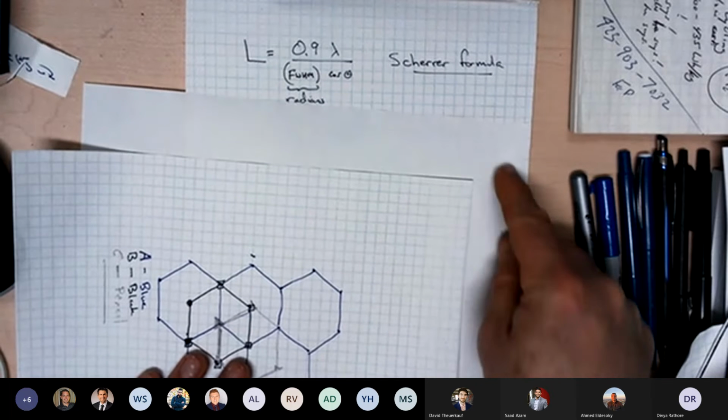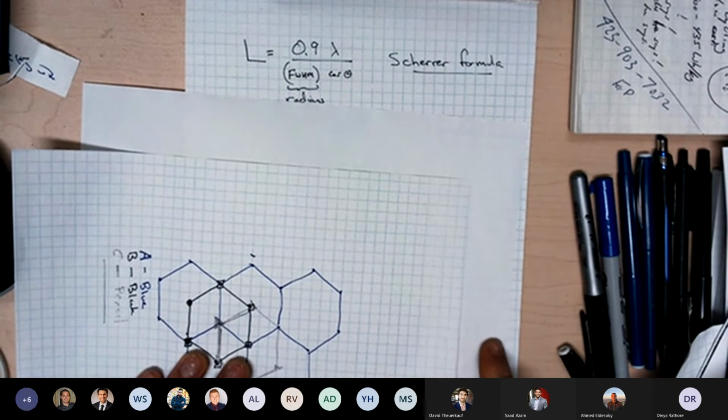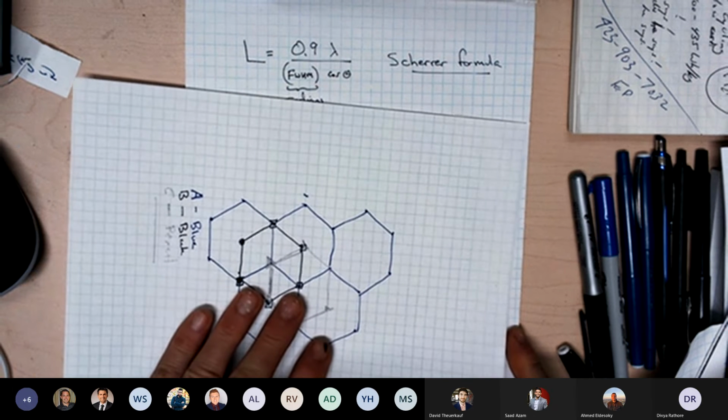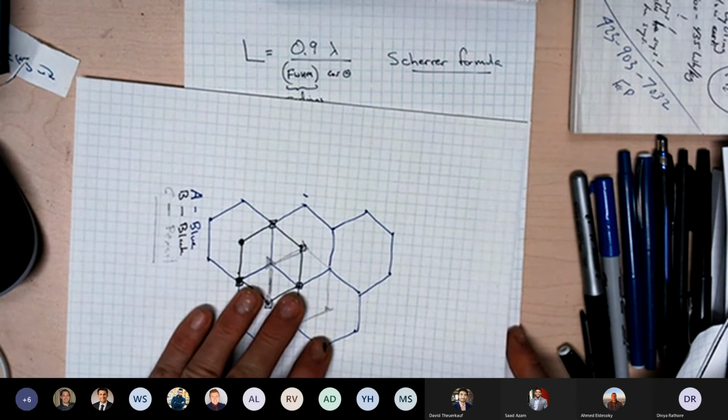I've got two graphene sheets. They're in AB stacking. Maybe I'll turn one of them over. Okay, so there's a white one and this one. You put lithium in between. They just have to slide 2 angstroms. 2 angstrom slide to go into AA stacking, okay?